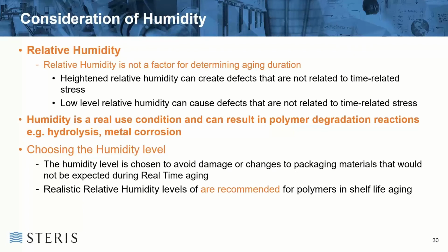But the problem is you need to have a realistic level of humidity in there. And what that is can be difficult at times to decide. Typically, if you're going to have a very high humidity level, you're going to create artificial defects that are not time related.